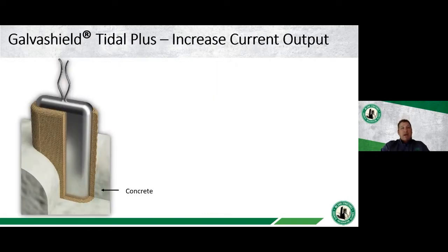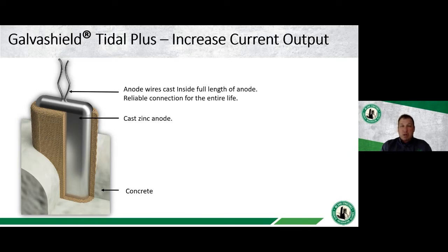So one of the methods that was designed was called the Tidal GalvaShield Tidal Plus. And the way that this can increase current output or galvanic current is it relies on a cast zinc anode. It's not an expanded zinc mesh anode, it's a cast zinc anode. So think of it as a larger bar of zinc. And it's actually going to be embedded in a concrete jacket. So you can see that there's a concrete substrate there. We have our cast zinc anode, but one of the big things to notice here is that we actually have a wicking fabric around the zinc core.